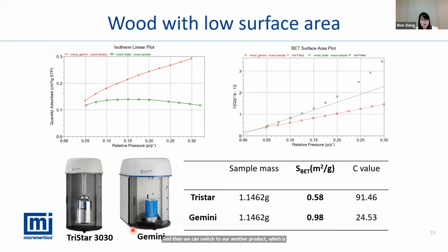When we use the Gemini to analyze the low surface area materials, we get a better isotherm, which is the red line here, resulting in an accurate BET surface area, which you can see from the red line. The BET surface area is about 0.98 square meters per gram. So in this case, we are saying that for low surface area materials, our Gemini can be a preferred way of running, offering a unique advantage over the TriStar.